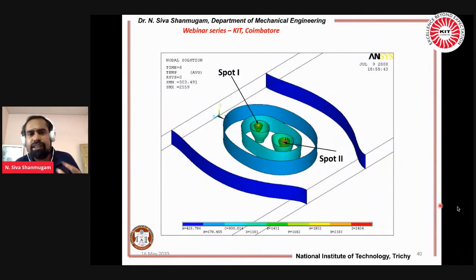You can see that at one time, one spot is cooling down while another is heating up. This information you can extract in the post processor. You can see the temperature is something around 2559 Kelvin. Minus 273 will give the approximate temperature distribution, and you cross the melting point of the SS, which is something around 1450, 1400. If you add 273, it's something around 1673 Kelvin. But the temperature I have predicted in the simulation is something around 2000, so it crossed the melting temperature. The area encompassed by the melting profile, where it is above the melting temperature, will give the approximate weld bead geometry.